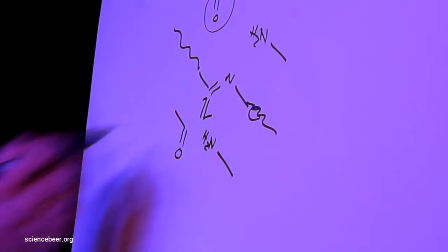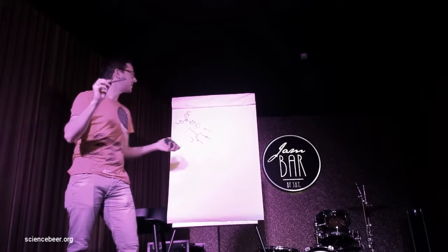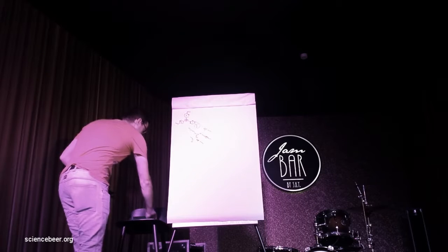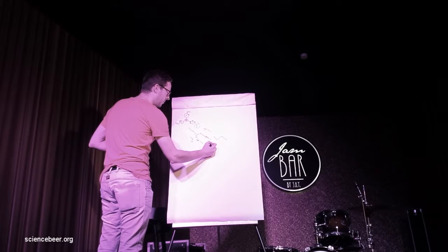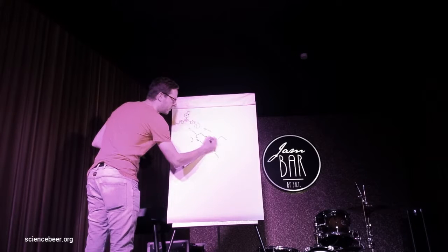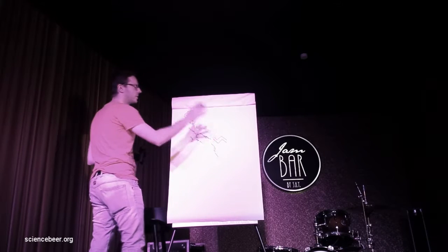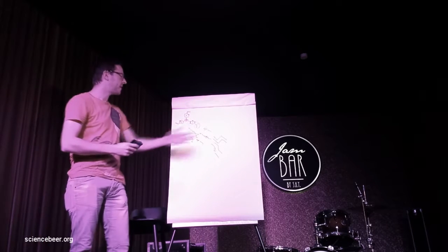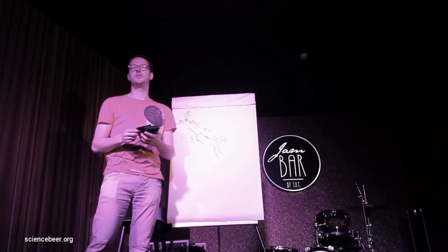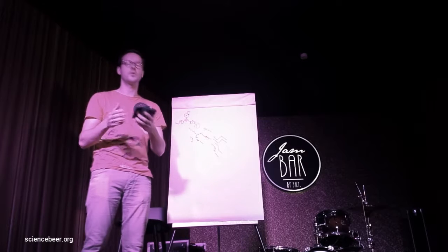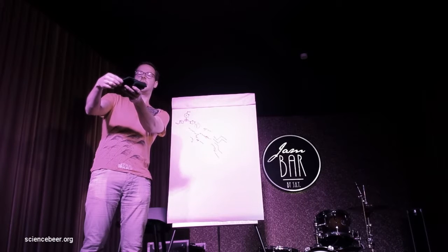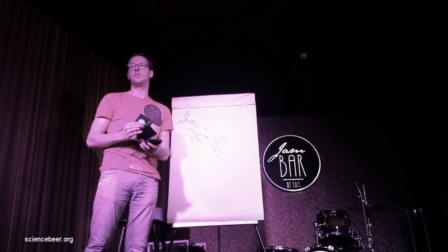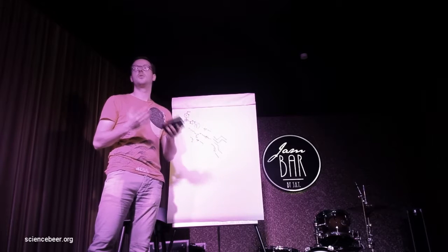It can be reversible. If you have one layer of a nice 2D material, and then on it another layer starts to react, and it doesn't work out because this group reacts not in this geometry, but for example in this one, it does not fit. You have maybe some layers when you look from top, and then one like this. So this will destroy this ordering. When this happens, a lot of times you will end up with an amorphous material, because just little defects will destroy your complete ordering, and you won't get another layer here, but you have these cracks and you won't have an ordering. So in the end you will end up with amorphous, non-ordered, non-crystalline material.